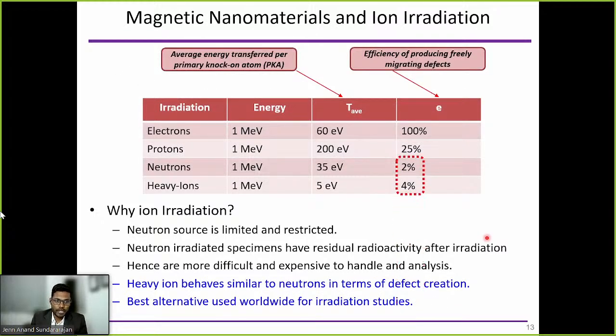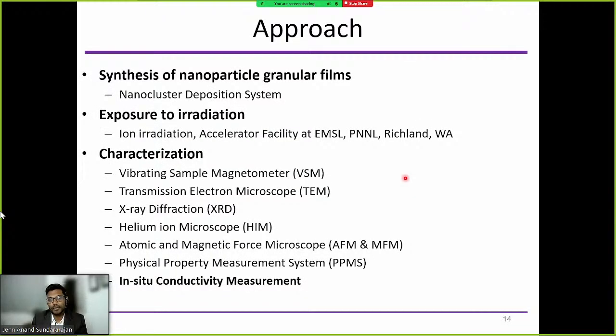And then we are using ion irradiation because we cannot use neutron irradiation. The reason we cannot use neutron irradiation is because the material is going to be radioactive, and we cannot handle it and cannot study it. So we want to use ion irradiation, which is equivalent to a heavy ion irradiation. As you can see from here, the efficiency is pretty much the same. So we use silicon ions just to replace the neutrons and to avoid radioactivity here. Okay, so our approach is to create nanoparticles, expose them to radiation, and characterize them before and after, pre- and post-irradiation of these nanoparticles. Let's do an apples-to-apples comparison to see how they actually behave, how the structural property, magnetic property, and intrinsic properties have changed over the course of time.